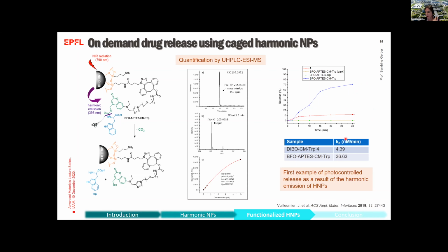And by measuring the kinetics of this release, you can see that this is really due to the harmonic emission of the nanoparticles, as the ligand itself has only a very small release due to the two-photon absorption capacity of the coumarin spacer. So this was really the first example of a photo-controlled release as a result of the harmonic emission of harmonic nanoparticles.